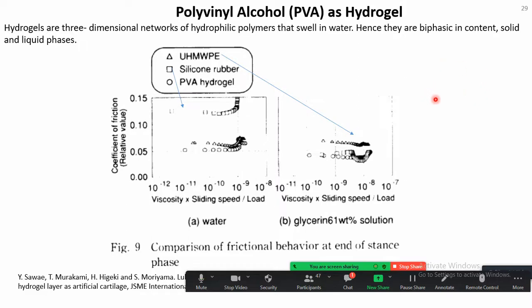Now I will talk about hydrogels. As far back as 1996, Sawai and co-workers did work comparing hydrogel against UHMWPE and found that hydrogel has equally good friction properties, although wear data was not available. The problem with hydrogel is that bulk mechanical properties are not good. These joints are load-bearing — the whole body weight rests on them — so the material must have very good mechanical strength as well as tribological properties. Hydrogels lack the mechanical strength needed, but tribologically they do very well because they contain a lot of water.